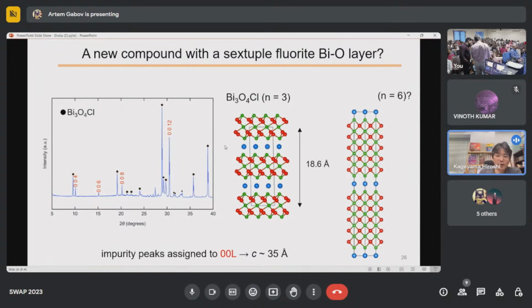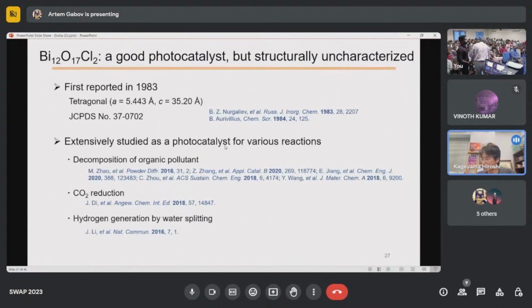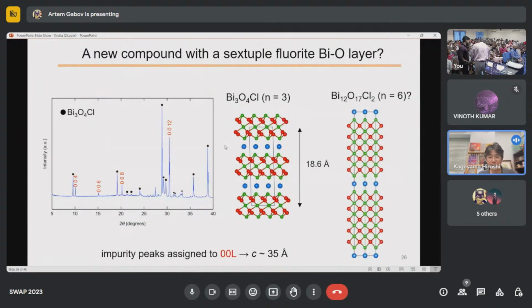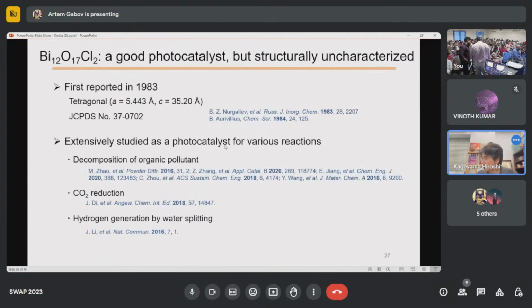which is nearly half of that of the tri-layer systems. So we speculated that this material has a six-layer fluorite-type structure. Then we got this composition, and later were disappointed to see that this compound was already reported nearly 40 years ago, in this paper. And recently, somehow, without knowing its structure, this material was found to be a very nice photocatalyst, as you can see in these papers.